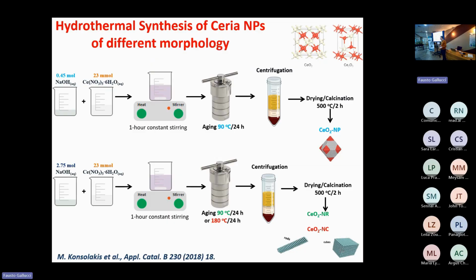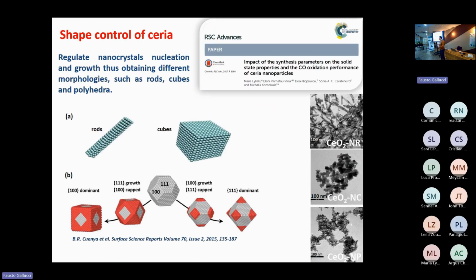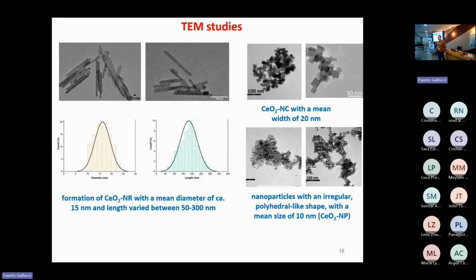By following the hydrothermal method and adjusting various parameters involving the concentration of precipitating agent, the aging time, and temperature, we can regulate nanocrystal nucleation and growth, thus obtaining different nanomorphologies like nanorods, nanocubes, or nanopolyhedra. Here you can see some indicative TEM images revealing the formation of nanorods with a mean diameter of about 15 nanometers and a length varying between 50 to 300 nanometers, nanocubes, and nanoparticles with an irregular, let's say, polyhedra-like shape with a mean size of about 10 nanometers.